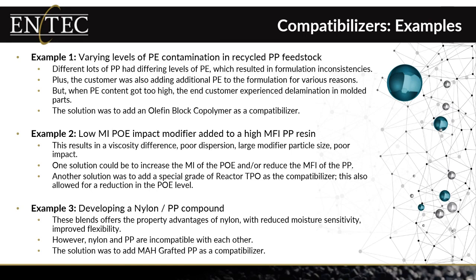So I had suggested to the customer to look at one of these olefinic block copolymers, which again works really, really well in polyethylene, polypropylene. And in fact, they used this, it worked very well. And in addition, because this product can be an impact modifier, they were able to actually reduce the level of impact modifier while using this OBC compatibilizer in their formulation.